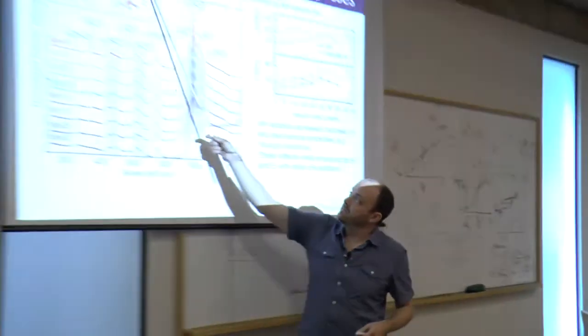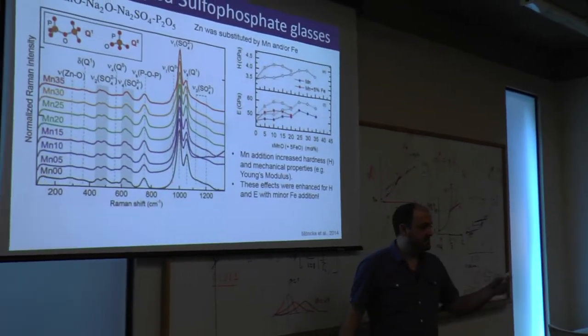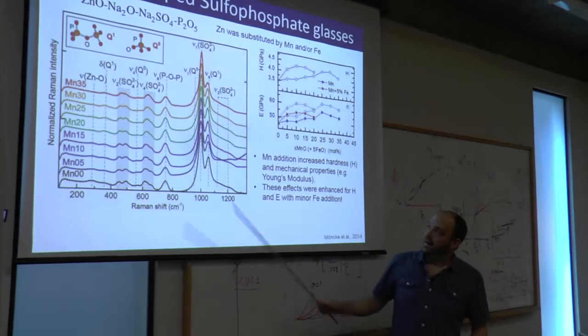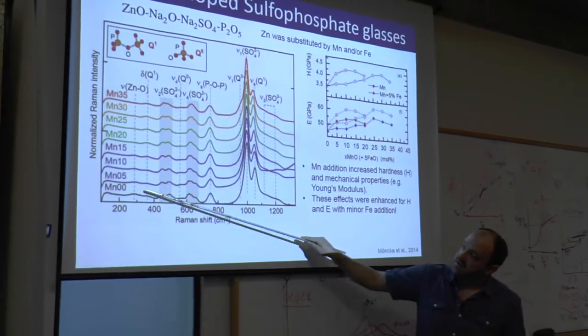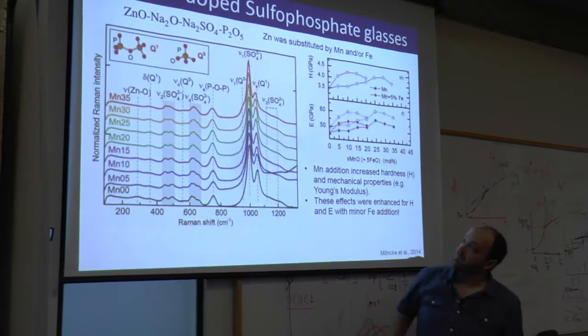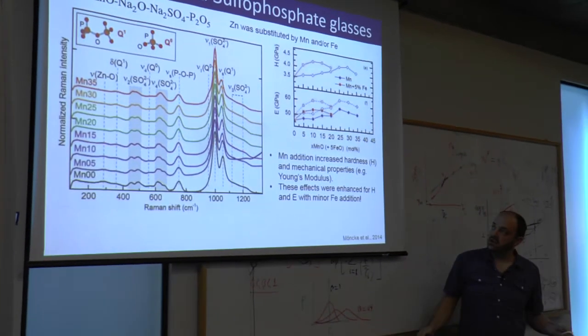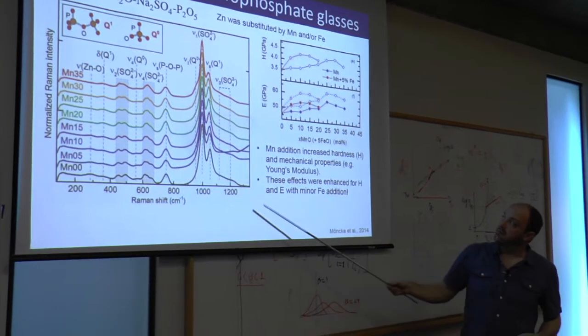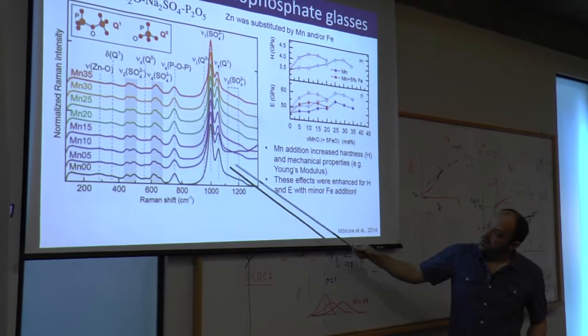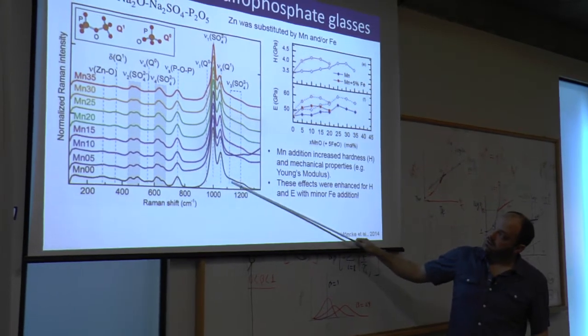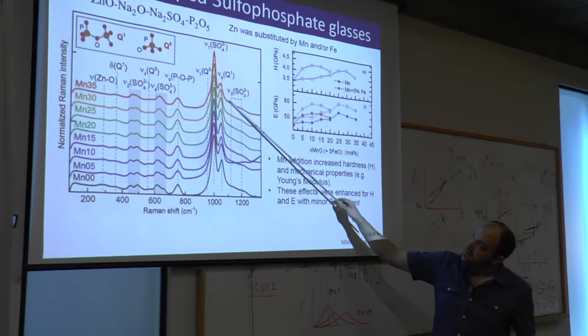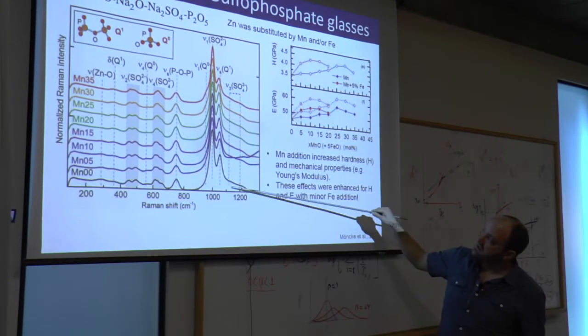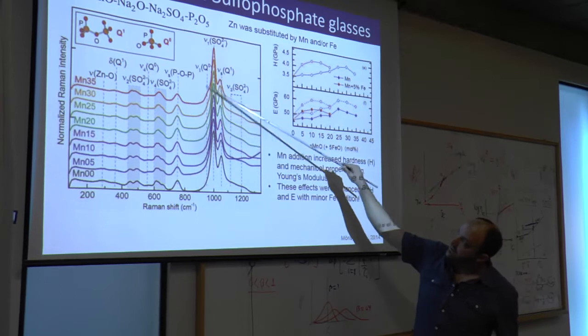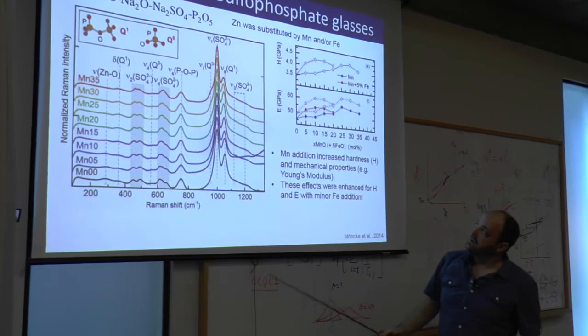Okay. Our next example is a sulfophosphate glass, and it has this composition. This is from Doris, so she's published this work, so if she wants to jump in, feel free. But the idea was that they exchanged zinc for manganese and looked at the structural changes following the addition of manganese. In the spectra, as we go from 0 manganese, so all zinc, to 35% manganese, we don't see a whole lot of change, but there are some subtle changes here in the shoulder where we might expect a Q0 species.